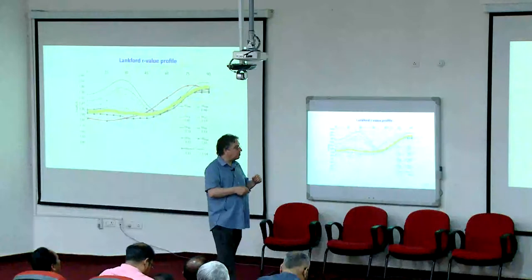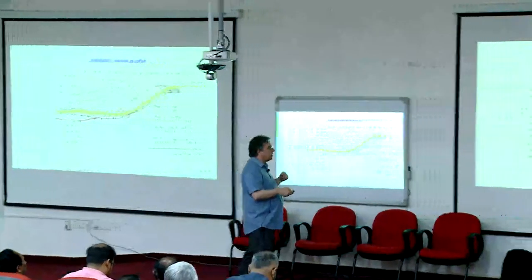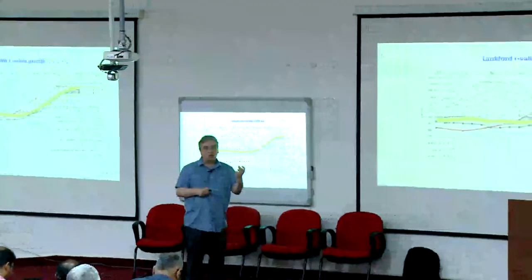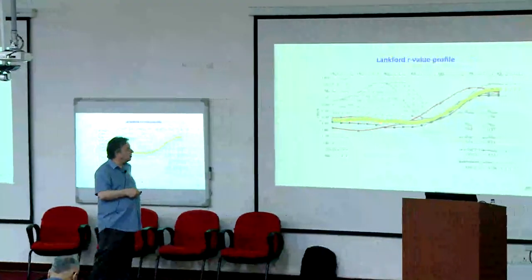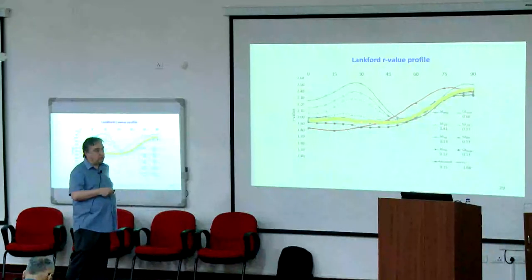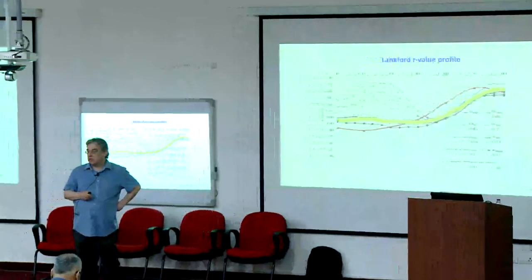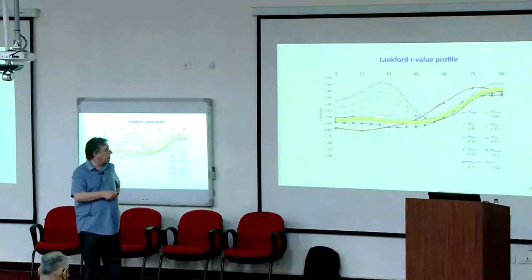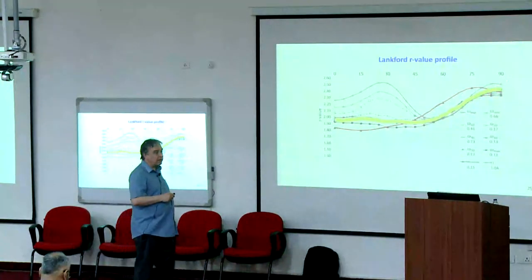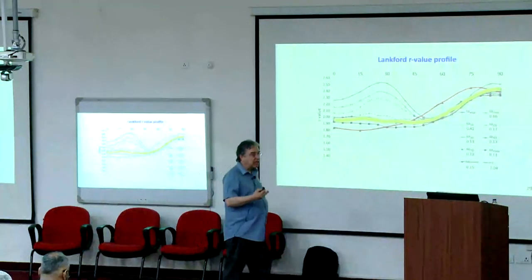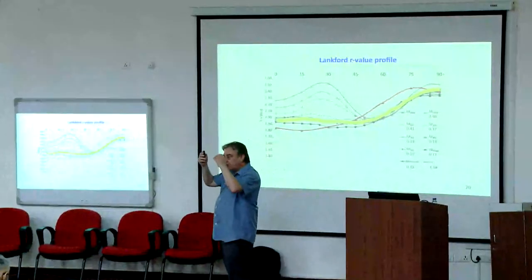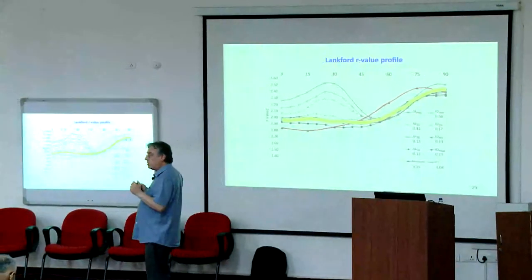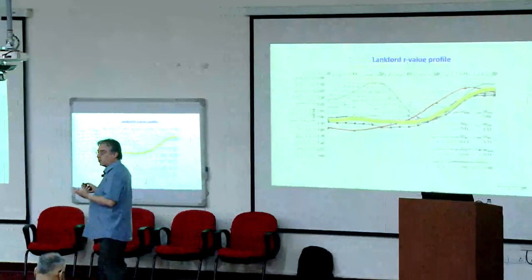Coming back to my story, even if you have the true topology that we put in our ALAMEL model, the result of our simulations of the R values are not that much better. So actually, it shows that to some extent, the R value is a mechanical property that is not really sensitive, between certain limits, to the topology of the microstructure.